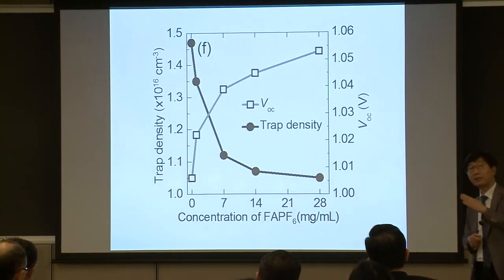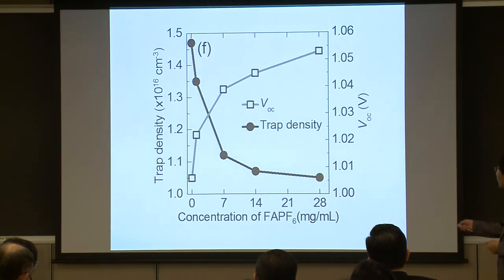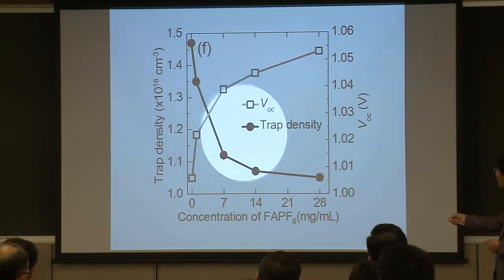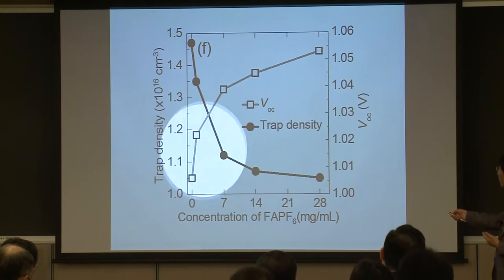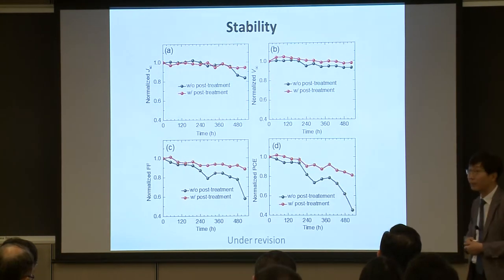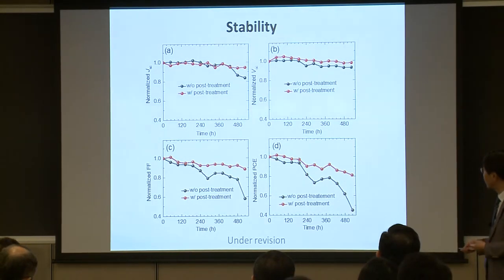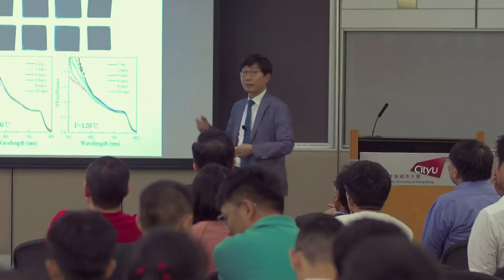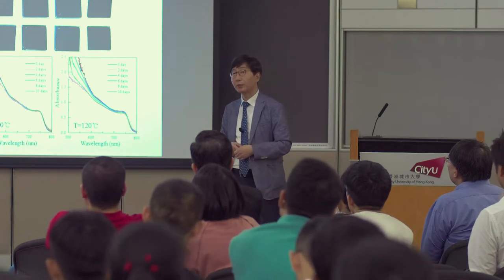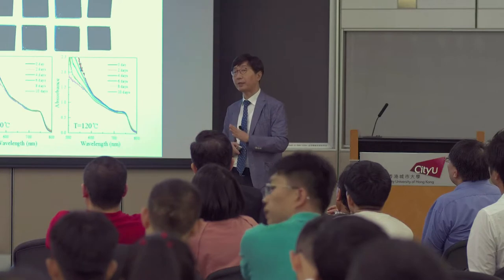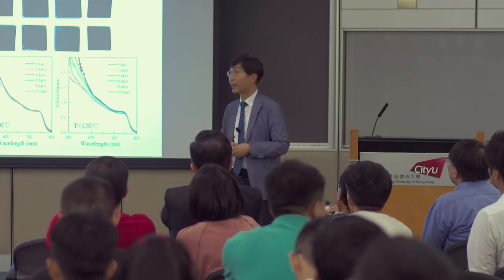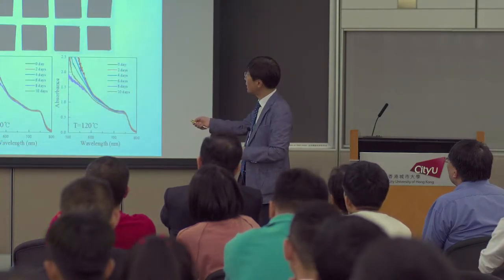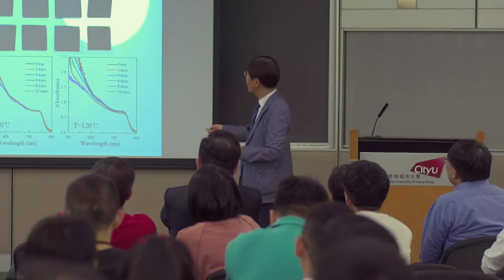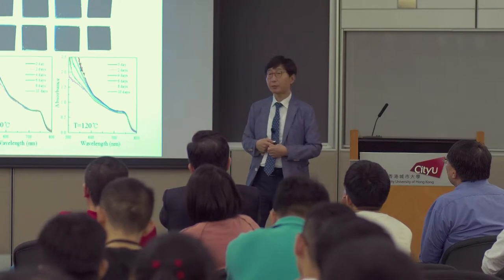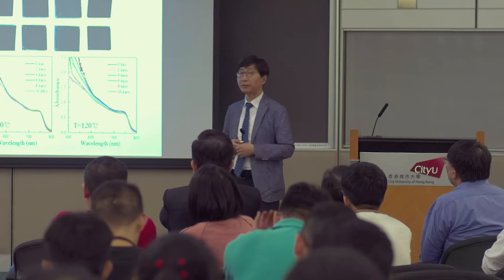And then to explain the increase of this open circuit voltage with the PF6 concentration, we estimated the trap density, and trap density slightly decreases with increasing PF6 concentration, which is correlated with the increase of the open circuit voltage. And also stability is improved as compared to the non-post-treated samples. Regarding thermal stability, which is very important, this solar cell passed the 85 degrees C thermal stability test. For the case of MAPbI3, we tested up to 120 degrees C, and after 10 days this perovskite is still alive, meaning that the perovskite material itself is thermally stable.